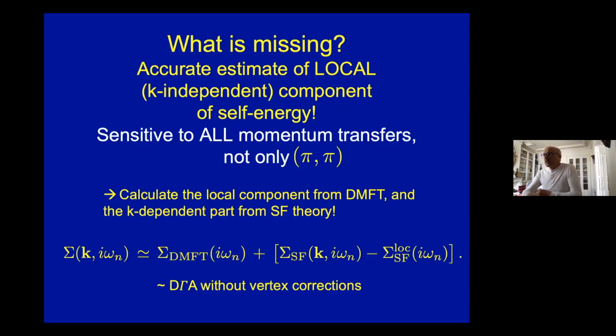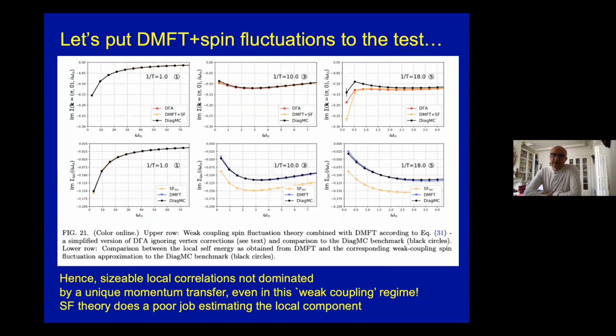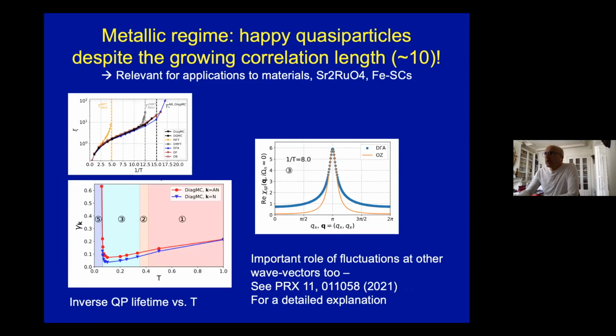There is an explanation of that, which I don't have time to enter into, but I refer you to the actual paper. So this obviously suggests combining dynamical mean field theory and spin fluctuation theory, and this is my sort of poor man's version of D-Gamma-A. This is D-Gamma-A without vertex corrections, like Thomas likes to say, which is just keeping DMFT as the computational method for the local components, and then using just one-loop spin fluctuation diagrams for the non-local components. And what you see here on this plot is that this does a very good job through all the metallic regime, and is even qualitatively reasonable in the pseudogap insulating regime.